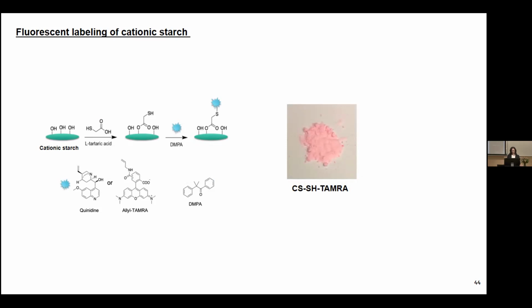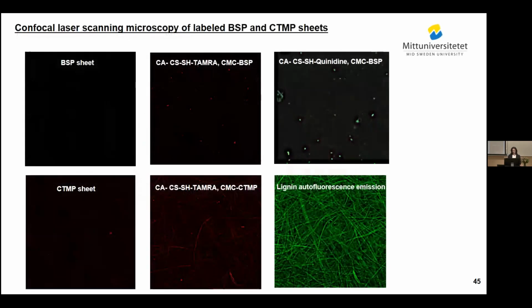Here also, this is the image with the allyl TAMRA. Then I applied this cationic starch the same as the previous method that I did for just normal cationic starch. And after preparing the sheet, I checked it with confocal laser scanning microscopy. In the case of bleached sulfite pulp, we have a heterogeneous distribution of this cationic starch. But in the case of CTMP, we have an even and homogeneous distribution of this cationic starch or polyelectrolyte on CTMP,